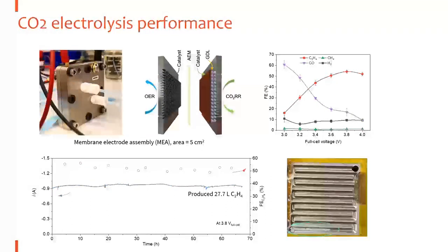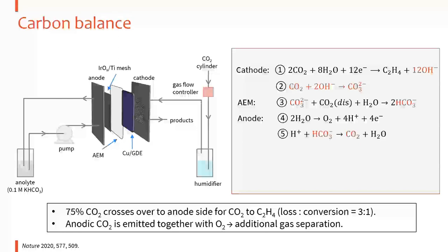So the reason we stop here is that the device is blocked by some salt in the gas channel, so that CO2 is not accessible by the catalyst. Then the cell has to generate hydrogen instead. So that means the cell is dead. So we are wondering why the cell is dead. So we do the carbon balance analysis. Here, you don't need to panic. Here is just the schematic of the MEA device.